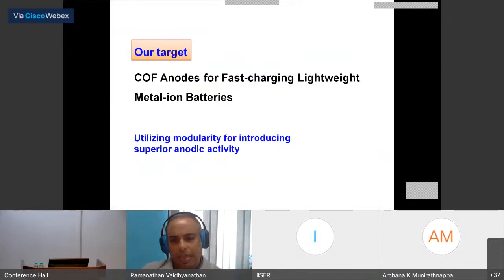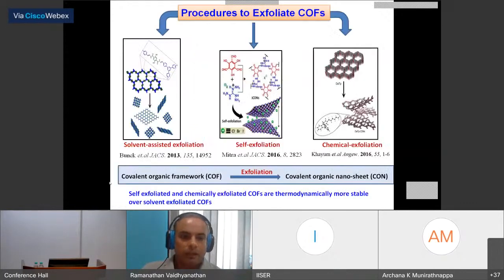So our target is COF anodes for fast charging, lightweight metal ion batteries. And we are going to use this concept of modularity to improve the anodic activity of COFs. So one of the key features of COF, another important feature, is that COFs can be exfoliated with a very easy procedure compared to graphite, for example, because the pi stackings of COFs are much lighter, in the sense they are at a longer distance, which means they can easily be exfoliated.